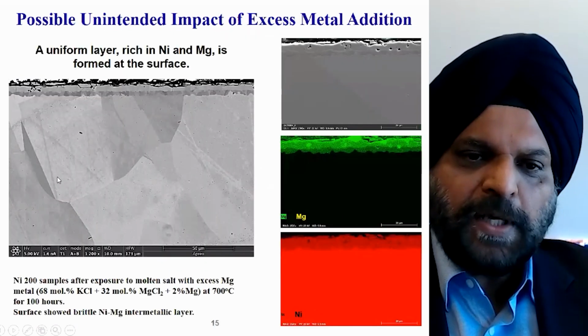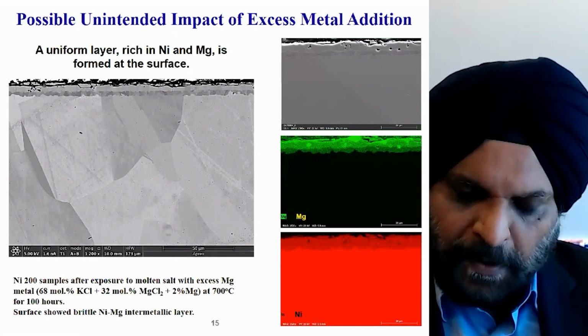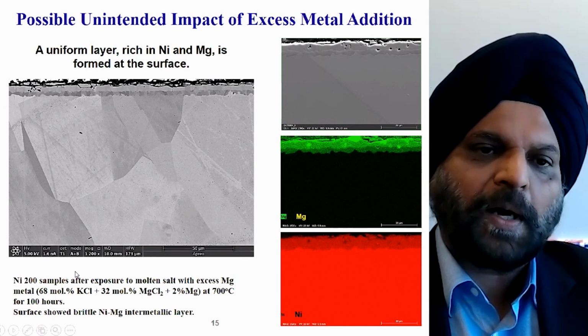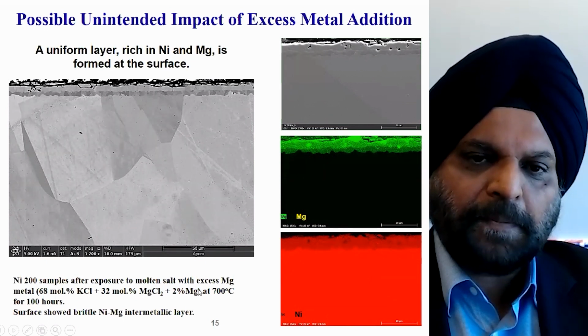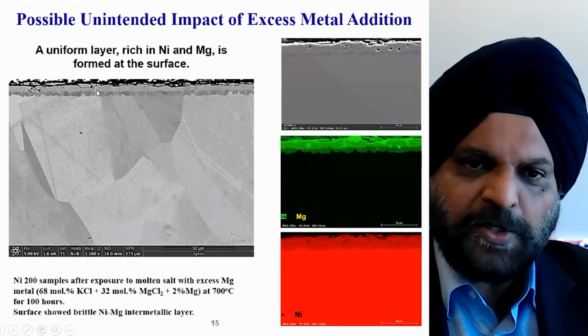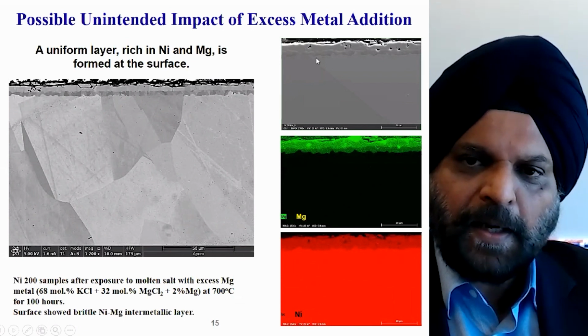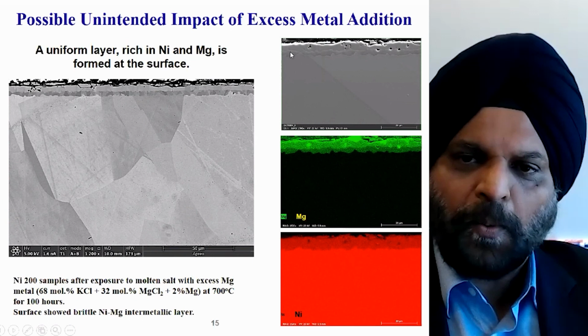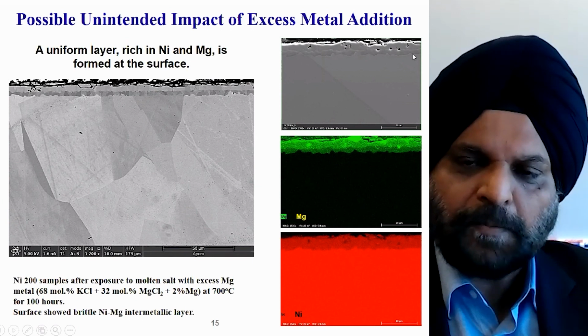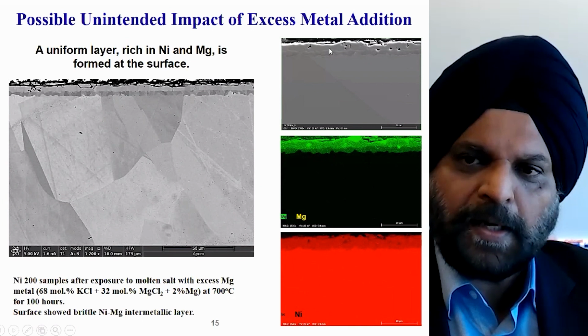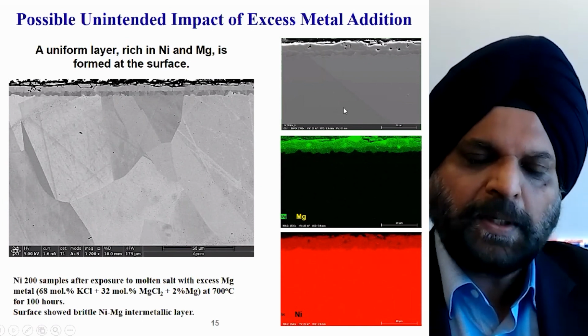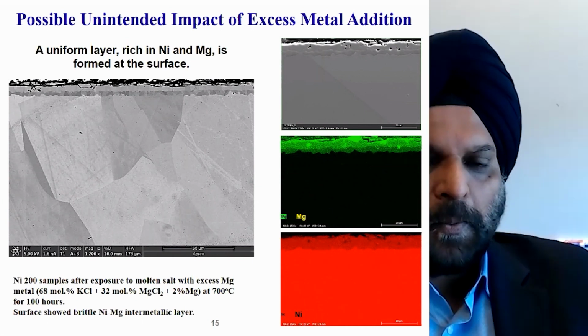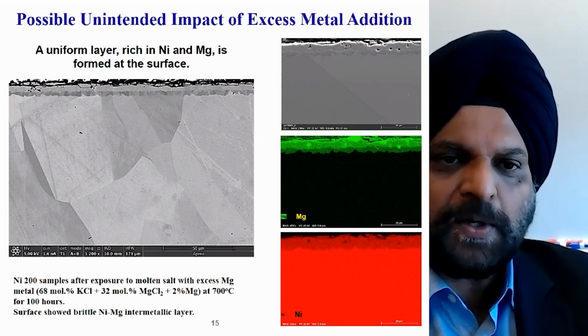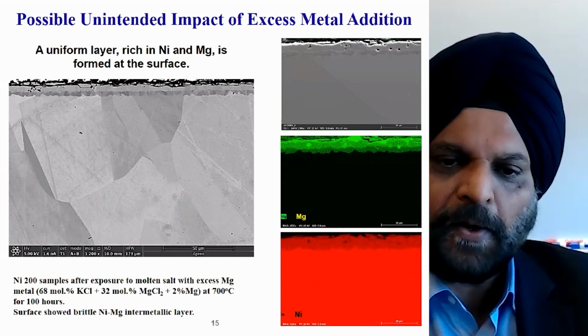To test that, we looked at our Nickel 200 sample, which is basically pure nickel, and looked at the cross section. After exposure with excess magnesium present, we actually see a dual layer. The inner layer, shown here in SEM, was rich in nickel because it's closer to Nickel 200, and the outer layer is rich in magnesium. So we got both MgNi2 and Mg2Ni in this sample. The problem is that if this happens on grain boundaries in the alloy, it can cause embrittlement.